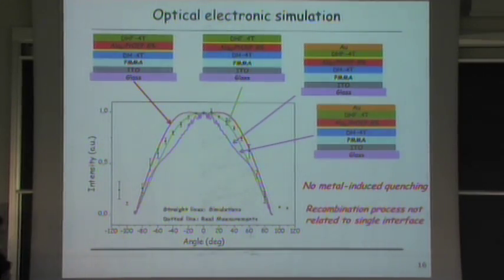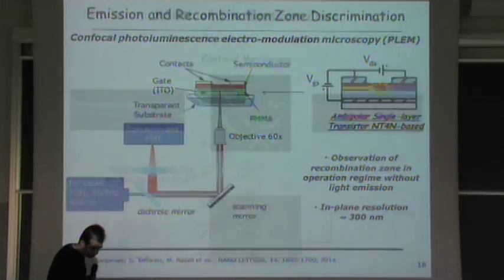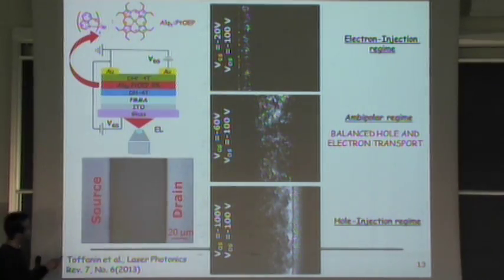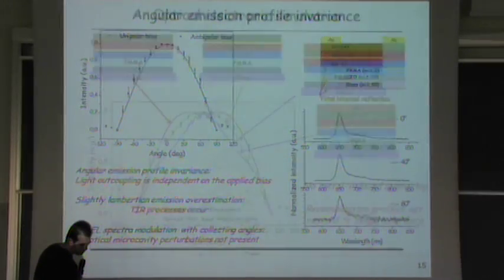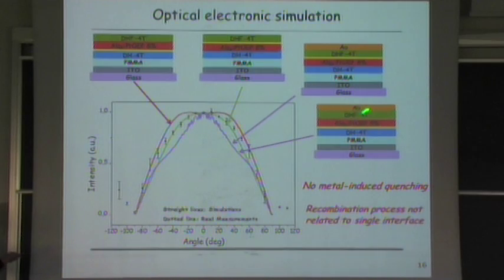We also did some optical electronic simulation. So here we used these two structures to approximate the OLED in the unipolar polarization condition. Because if you remember the image here, in unipolar polarization you have the emission under the electrode. So we use this kind of multi-layer structure with gold on top. In the case of the ambipolar regime, we don't have the gold on top, so we used these two multi-layer